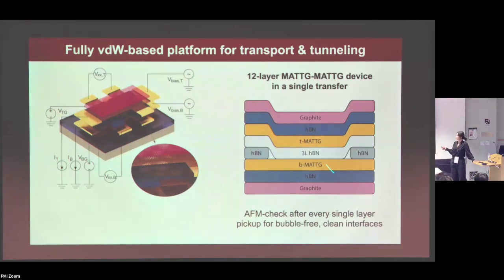But here, the important experimental thing that we did is that we made sure there's another thin, but not tunneling thickness, hBN that's also coexisting here, and we open up this circular window in the middle of our device, so that the tunneling between these two devices only happens in this very center region. And where's the center region? The center region is exactly where you would be measuring the core of the whole Hall bar devices of both magic angle twisted trilayer graphene.